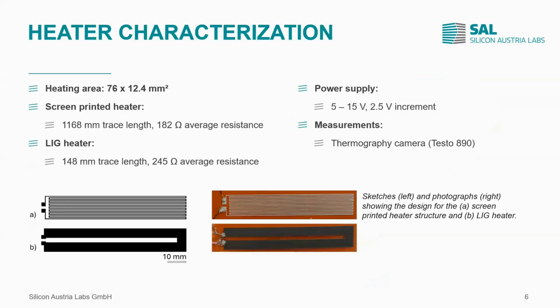So let's come to the characterization of the heaters. The screen printed heater consists of 8 meander loops with 500 microns width and also 500 microns spacing in between, while the LIG heater only consists of 1 loop. Like I said before, this is because we wanted to achieve similar resistance measurements to be able to compare them. Then we applied a DC voltage from 5 to 15 volts with 2.5 volt increments and monitored the heaters with a thermographic camera.